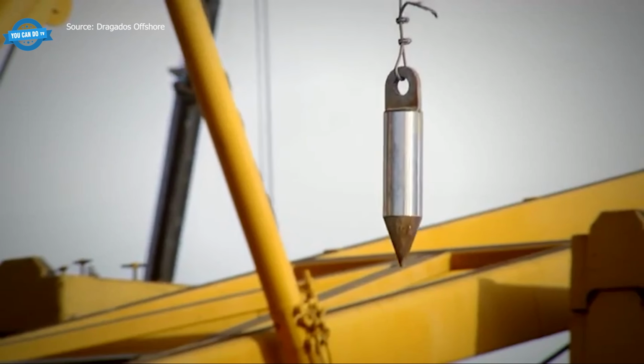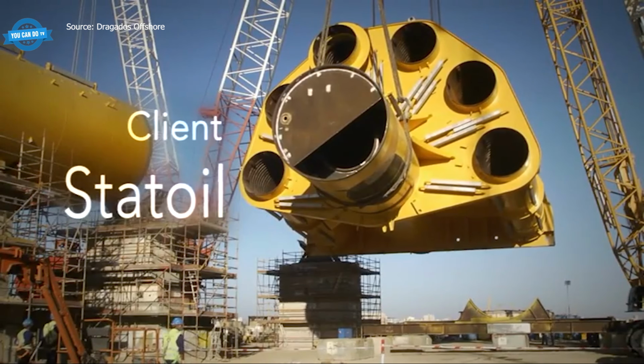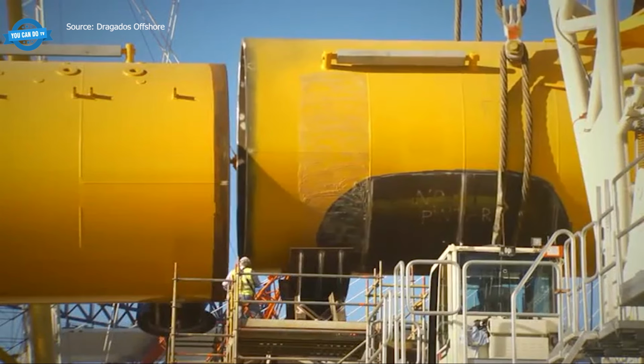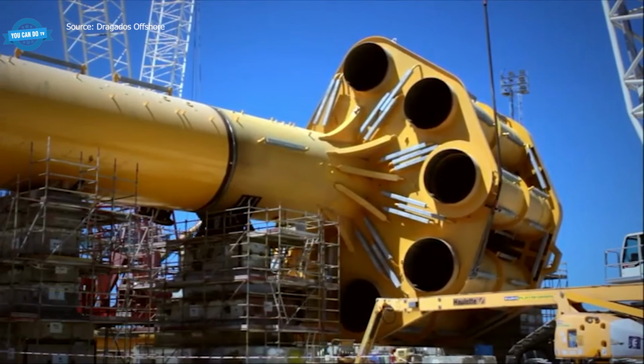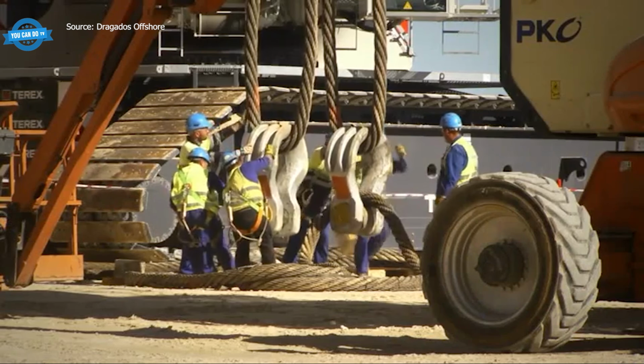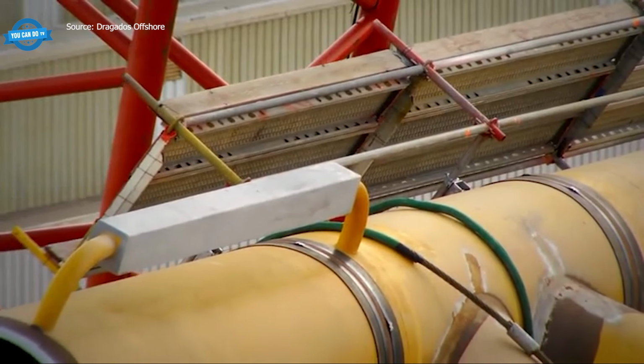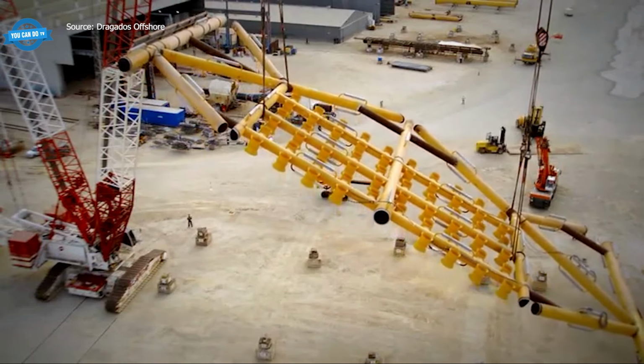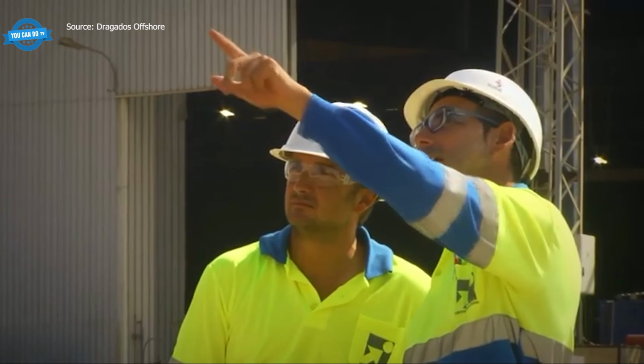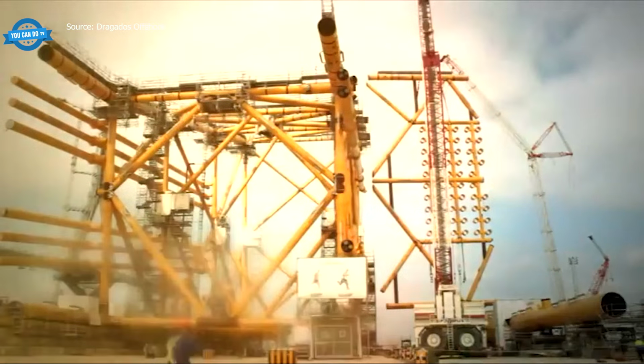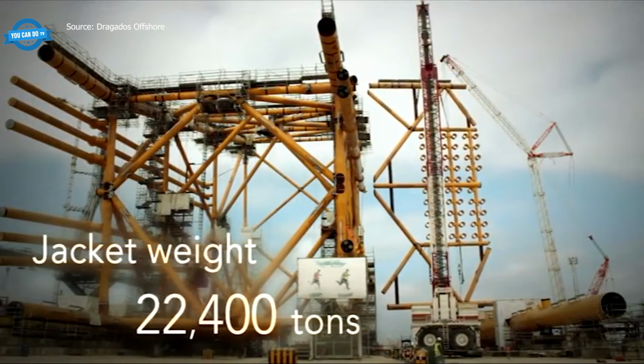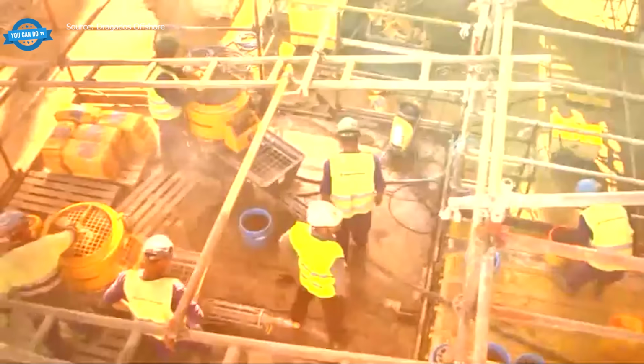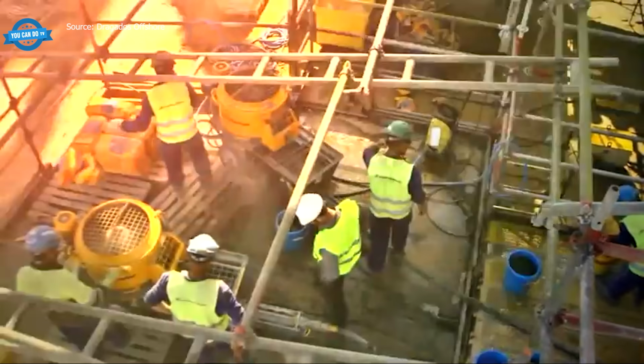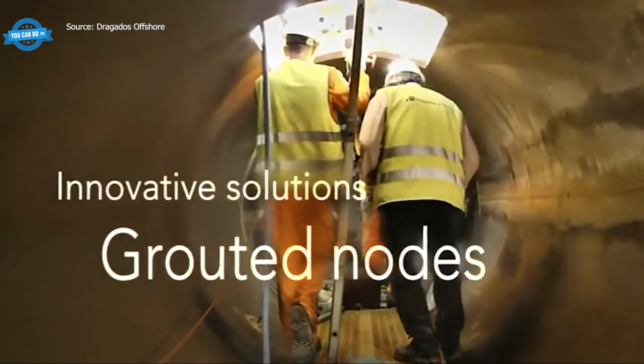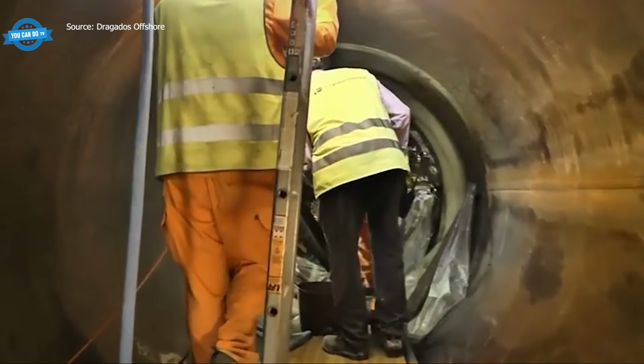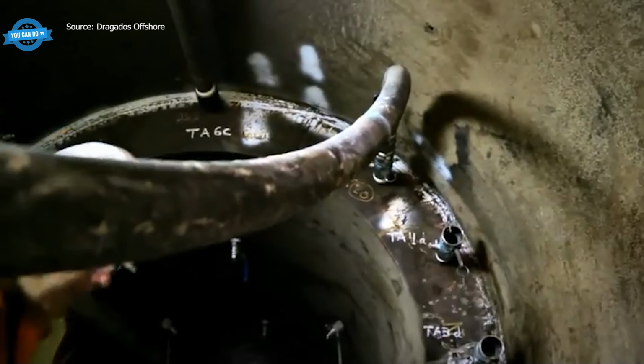At the Mariner offshore field, located in water depths between 97 and 112 meters, around 130 kilometers off the British coast, an 8-legged launch jacket was fabricated as the structural backbone of the project. The jacket itself weighs 22,400 tons, with a roll-up weight of 4,500 tons, and it is engineered to support more than 50,000 tons of topside structure. Weld repair rates stayed remarkably low at 0.6%.